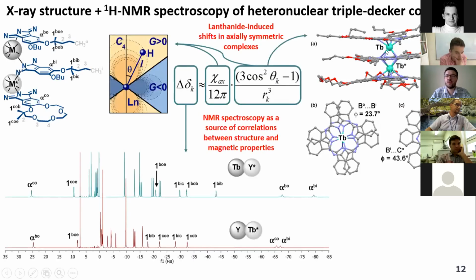So we used NMR spectroscopy to get insight into the influence of these structural properties on their magnetic behavior. This analysis was made due to the well-known equation which correlates the lanthanide-induced shift observed in the NMR spectrum, the axial anisotropy of the metal ion, and a geometric parameter which is associated with polar coordinates of the considered proton with respect to the metal center. So we made this analysis. We used the X-ray structure for the assignment of the NMR spectrum, and then we made the opposite direction studies.